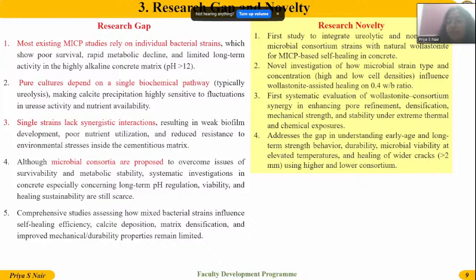So my research novelty, as I already told, is that I am using two kinds of bacterial system: one is ureolytic and the other is a non-ureolytic consortium. I am using two kinds of cell concentration, one higher and the other lower bacterial concentration, with a 0.4 water-cement ratio. And I am introducing a new material. It's already used elsewhere, but in self-healing it is the first attempt: wollastonite, a calcium-rich natural mineral material, which I have introduced in the system.